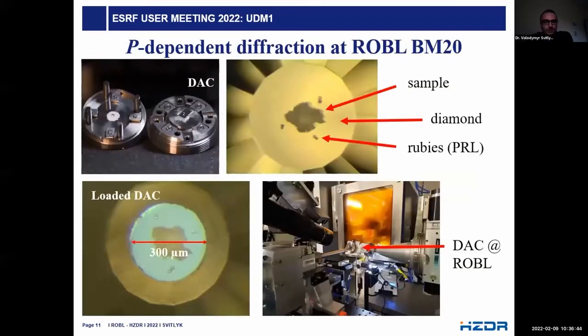Okay, so when it comes to pressure, we used diamond anvil cells kindly provided by the ESRF high pressure laboratory for this experiment with cerium-doped samples. And it was actually the first high pressure experiment at the ROBL beamline. It was done last year. Here you see the setup. This is now the XRD2 diffractometer, the multi-purpose diffractometer. Here is a diamond anvil cell mounted on a uniaxial goniometer. And here we have a large Pilatus 2M photon counting detector.